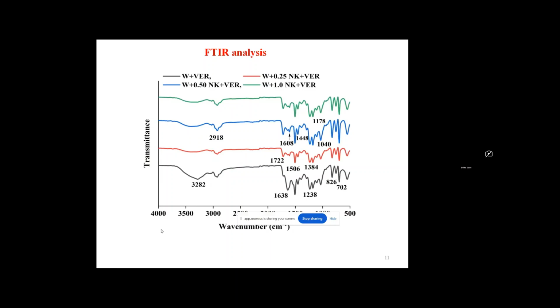So here we found that there is no chemical bond formation between the resin and the wool fiber, because the resin, obviously, is hydrophobic in nature and the wool fiber is hydrophilic in nature. So there is no scope for making a chemical interaction. In fact, it is a physical adhesion. That is the reason behind the strength of the composites.